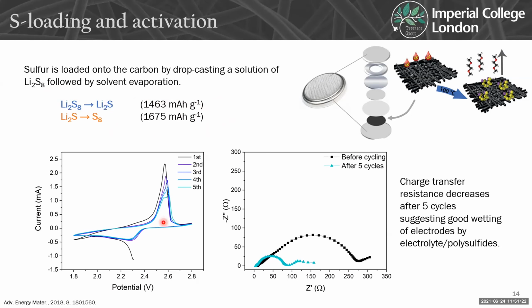So from the CV we can see that we've got the typical reduction and oxidation steps here that go quite nicely, and then impedance before and after cycling, we can see that the charge transfer resistance decreases after 5 cycles, and that suggests that with the cycling we are improving the wetting of our electrode, which again is a good thing in terms of the interaction of the carbon with the electrolyte and the polysulfides in solution.